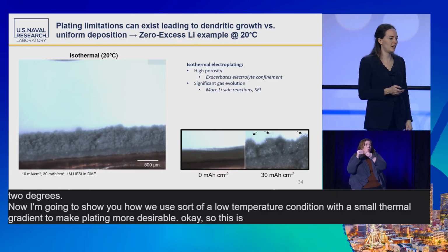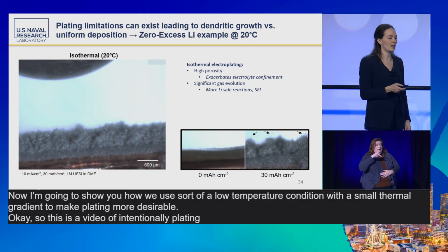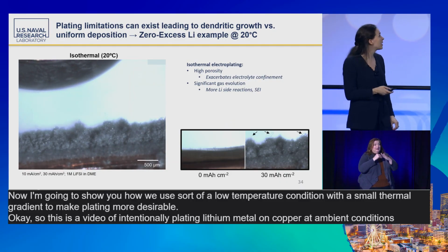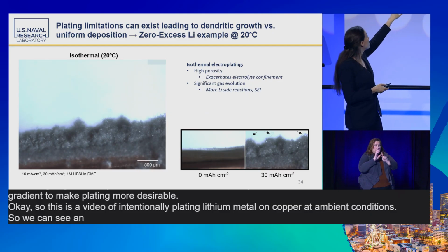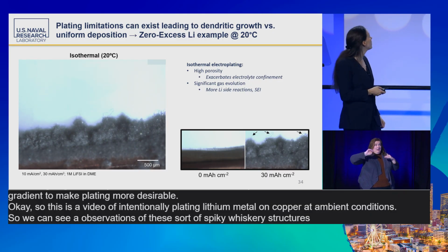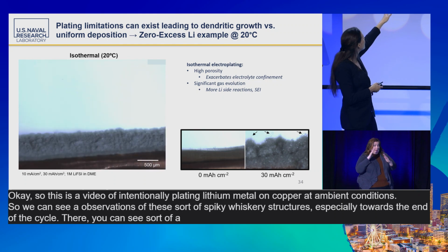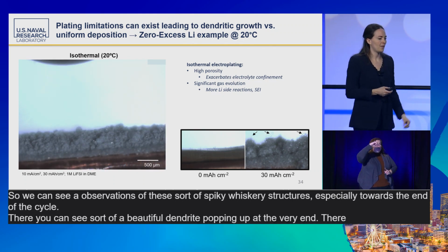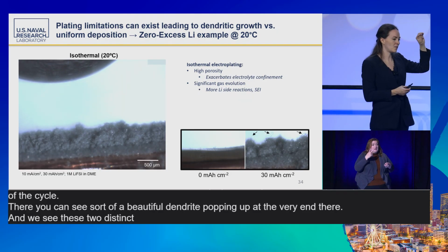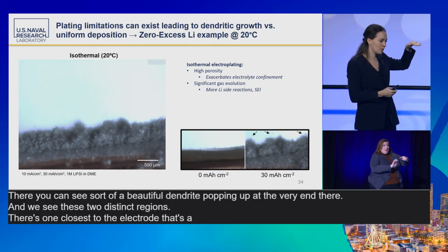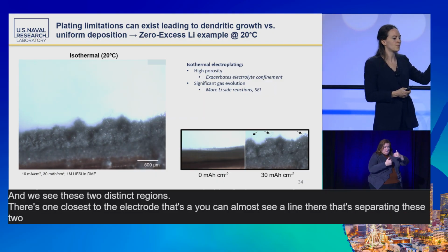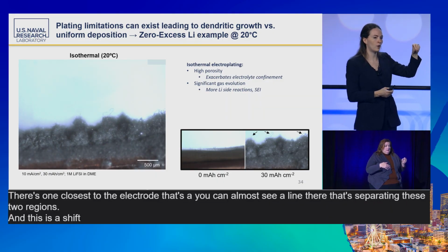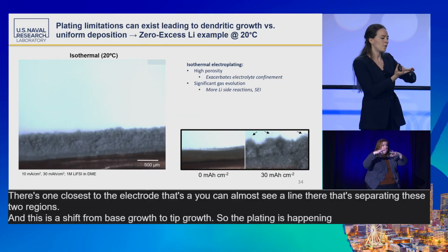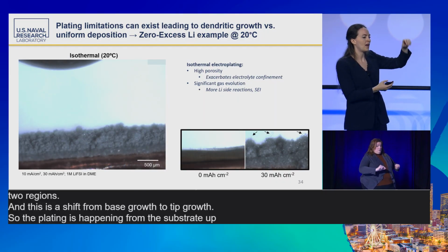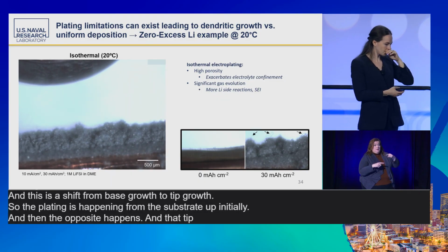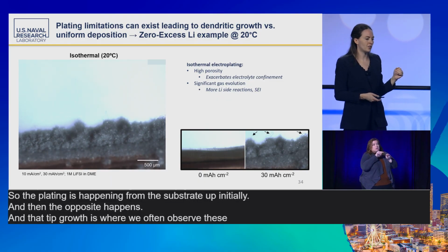Okay, so this is a video of intentionally plating lithium metal on copper at ambient conditions. We can see observations of these spiky, whiskery structures, especially towards the end of the cycle there. You can see a beautiful dendrite popping up at the very end there. And we see these two distinct regions. There's one closest to the electrode, where you can almost see a line separating the two regions. And this is a shift from base growth to tip growth. So the plating is happening from the substrate up initially, and then the opposite happens. And that tip growth is where we often observe these dendritic features.